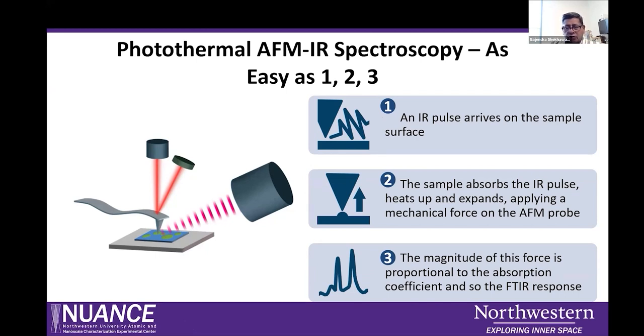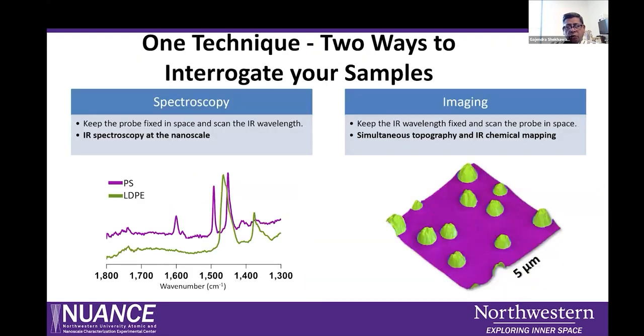Here we also use the normal silicon probe. In the case of a Raman TERS system, we use a very specialized probe, and the probes themselves are a little costly. But here we just use the traditional gold-coated cantilevers. They are not that costly. There's no standard specific probe for that. It's a pretty normal probe.